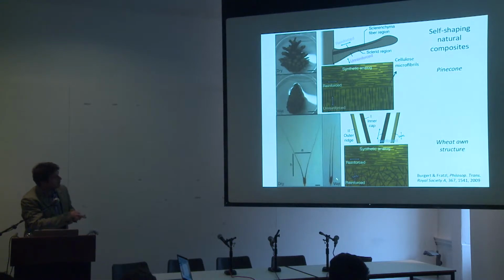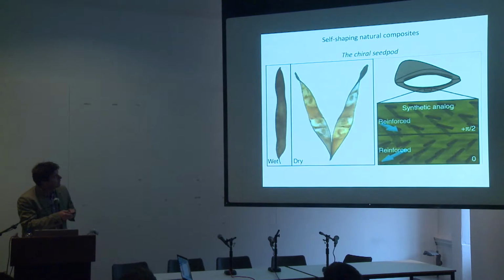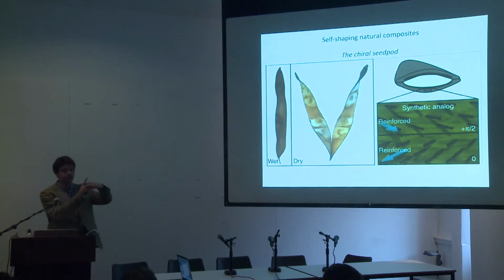The exact same idea, though in a slightly different configuration, is seen in these little hairs of the wheat awn structure. Here we have, again, this bilayer. Again we have the fibers orthogonal to one another, but this time you have them tilted by 45 degrees with respect to the long axis of the system. And therefore you don't have pure bending, but you rather confuse the system and lead to this twisting as the minimum energy configuration.